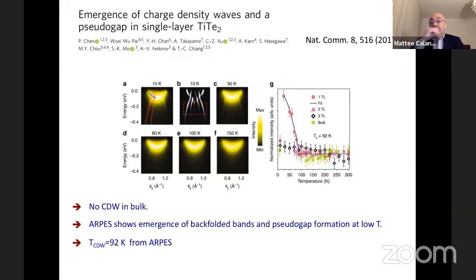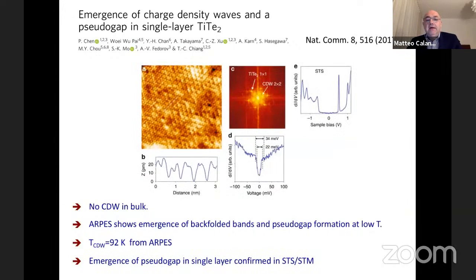This is not strange in the sense that the phonon spectra, of course, change when you replace selenium with tellurium. However, what is strange is that you have an instability that comes out only when you thin the sample and not in the bulk. And you can see that the instability can be very well seen. So we have a very big pattern in the single layer.